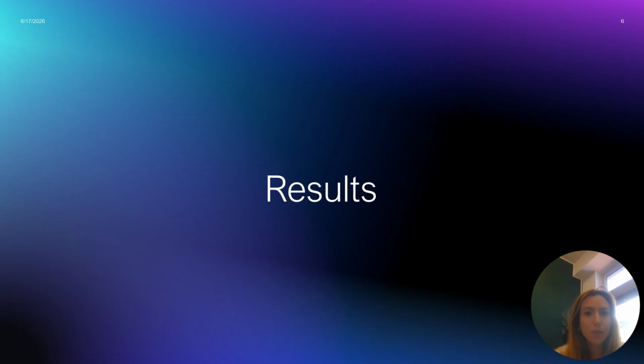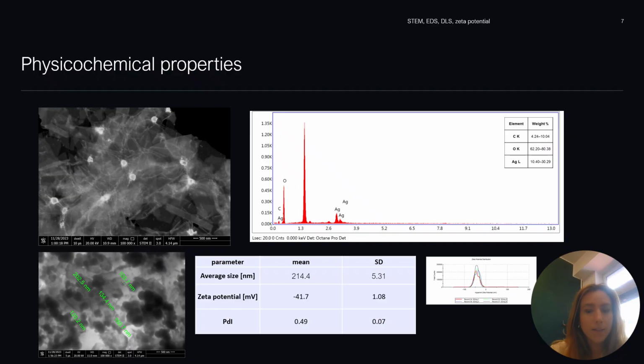With the methodology established, let me now move on to the results and examine the performance of the developed nanocomposite and the textiles. Dynamic light scattering showed an average particle size of approximately 214 nanometers and a zeta potential of minus 41.7 millivolts, indicating a good colloidal stability.